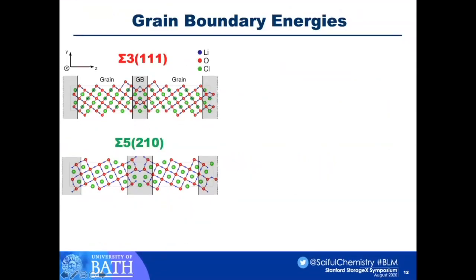So the starting point is to look at different grain boundary energies and grain boundary structures. On the left, we've got a ball and stick model of sigma 3 and sigma 5. Even if you don't know the notation, don't worry: the sigma 3 is a bit more close packed at the grain boundary. Sigma 5 tends to be more open, with lower coordination at the grain boundary structure.